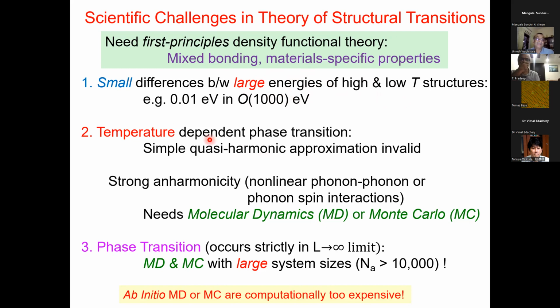I'll come to this point within a few slides, by the way, because this is still a challenge for standard density functional theories. The second is that these phase transitions are dependent on temperature. So here, the quasi-harmonic approximation of phonons is not quite valid. Phonons are highly anharmonic, and that's actually what is reflected in the double well energy function. And that means the nonlinear phonon-phonon or phonon-spin interactions can be very strong. And you need molecular dynamics or Monte Carlo simulations to study the thermodynamics of such a strongly anharmonic system. Unfortunately, you can combine ab initio, or first principles, with MD, but a phase transition occurs strictly in the large size limit. And there, these simulations are very impractical, because doing ab initio MD for tens of thousands of atoms is computationally too expensive.